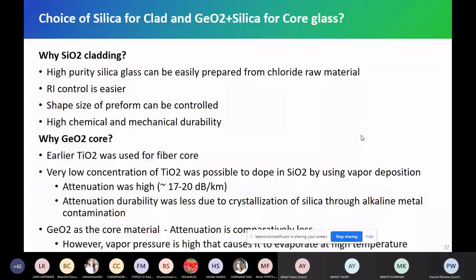Germanium was very good. Losses were limited. Scattering there is limited to 0.2, 0.35, something like that. So GeO2 became a very popular material. So we now have SiO2 cladding, GeO2 core. It is not pure GeO2; it is GeO2 plus SiO2, and germanium is a very small amount.